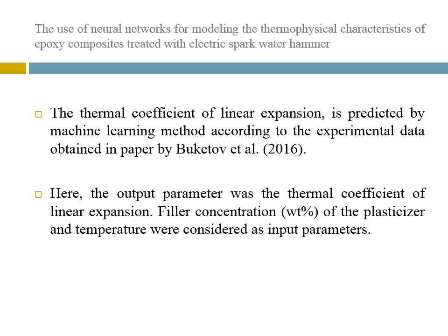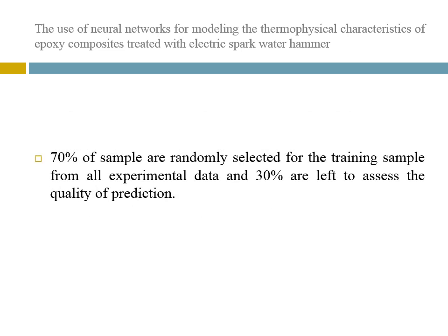The thermal coefficient of linear expansion is predicted by a machine learning method according to the experimental data obtained in the paper by Buketov. Here, the output parameter was the thermal coefficient of linear expansion. Filler concentration and temperature were considered as input parameters. During learning, the dataset is divided into two unequal parts: training and test samples. 70% of samples are randomly selected for the training sample from all experimental data, and 30% are left to assess the quality of prediction.